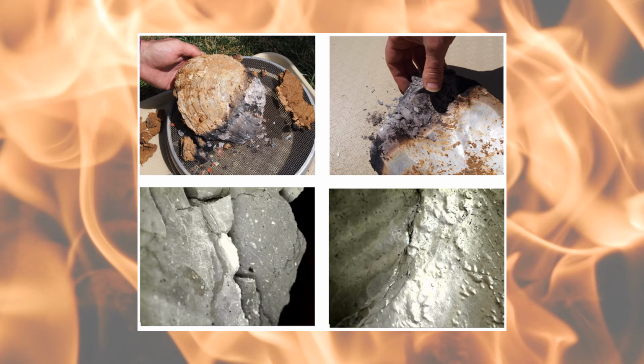But one of the first responses, and you could actually hear it, was that the water within the shell structure, you could hear it bubbling, and it was steaming away. And I mean, potentially the organics were part of that as well, but you could see this bubbling on the surface, as you can see in the bottom right image, that was actually deforming the nacre.